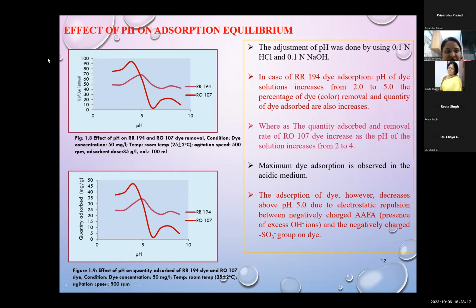The first parameter is pH, the effect of pH on adsorption equilibrium. The adjustment of pH was done using 0.1 normal HCl and 0.1 normal NaOH. In the case of reactive red dye, as the pH of the solution increases from 2 to 9, the percentage of dye removal changes.